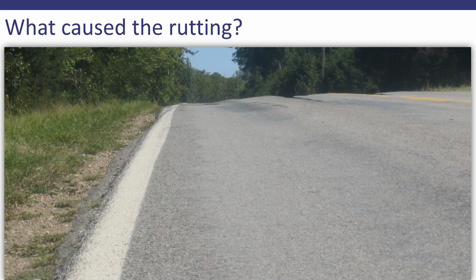The other indication of mixture rutting is that the stripe moves a bit. It's not super straight. So right through here, it looks straight, and then it's pushed out a little bit. That is also an indication that we've got some mixture rutting. That surface has moved. They didn't paint the stripe crooked, hopefully, but that tells us that that mix is moving a little bit. Now, based on core samples, we also found that there was some subgrade issue, and we had to deal with that as well.